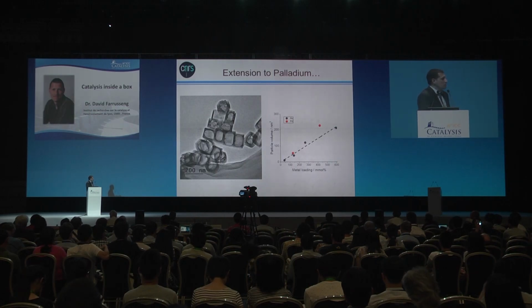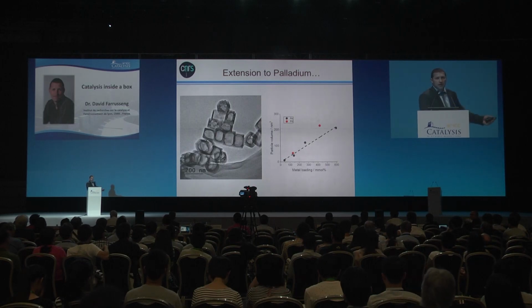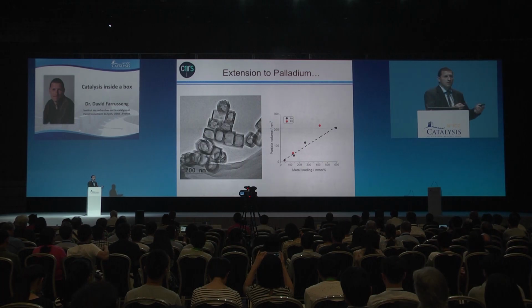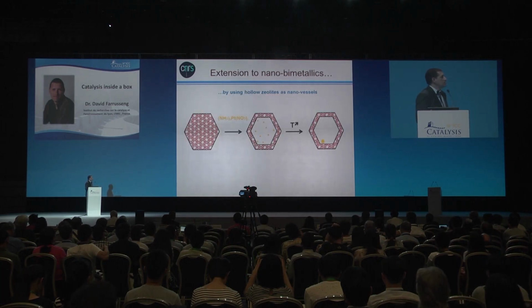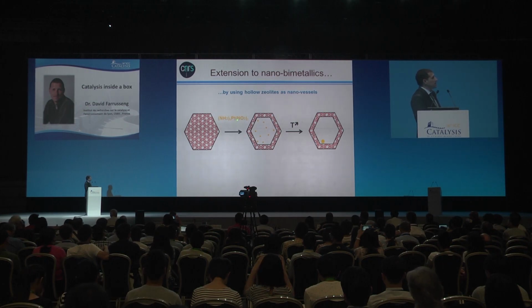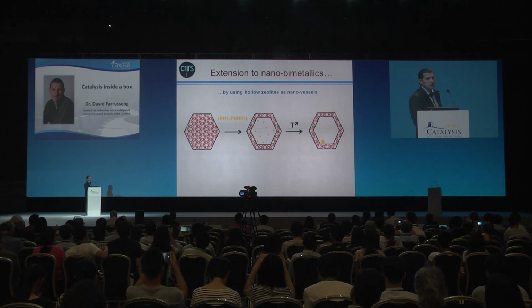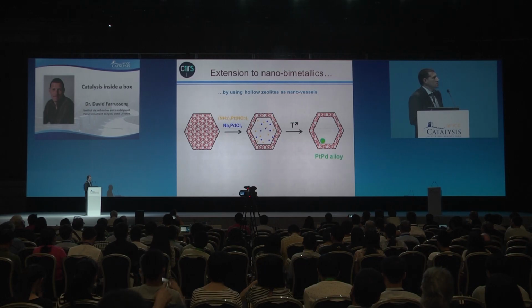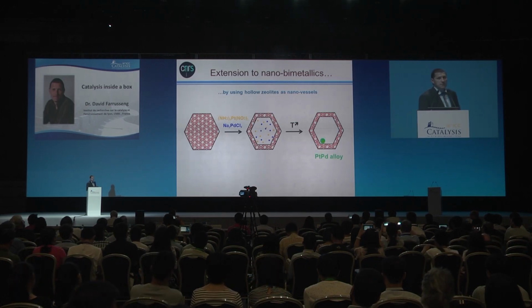And furthermore, it means that if we can control at the same time the platinum and the palladium, we can also control the composition of an alloy if we put them together. And this is what we did, for example. This is a cartoon for platinum, sorry. We can control the platinum content, which eventually leads to nanoparticles. If you add palladium, then eventually you will get a Pt-Pd alloy.